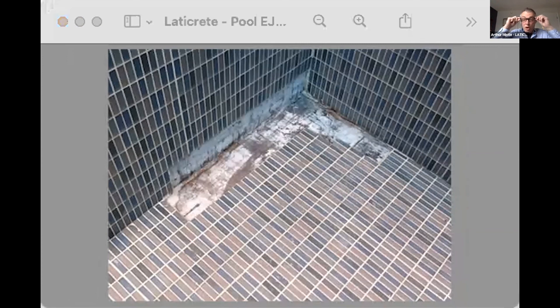This steel tank also lacked proper movement joints, and tiles buckled into the corners — no movement joint at the vertical corner meeting the two horizontals. The argument was 'it's steel, how much movement is there?' But steel tank manufacturers actually recommend pre-filling the tank before tiling to stretch it and allow proper expansion. Steel tanks will expand and contract and require proper movement joints. Fortunately, this was a localized pop-out rather than widespread damage.